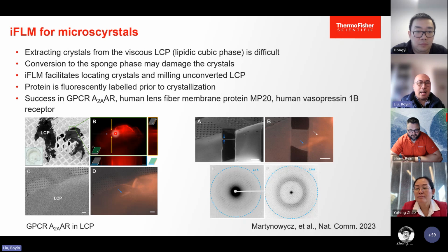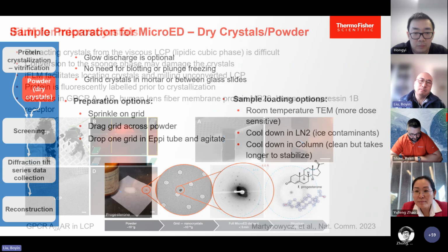And then you can aim for the area, and iFLM also gives you the precision in the Z direction. Then you'll be able to find where exactly the lamella is. After the milling, you switch on the iFLM again. You can see there's a piece of GPCR crystal here, and then you aim for the crystal on the lamella, and you get very good diffraction.